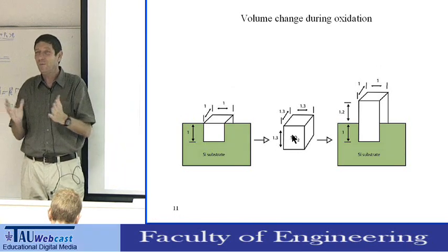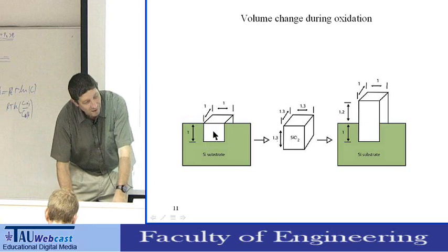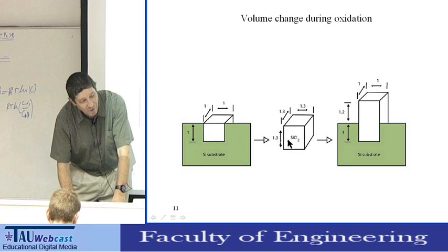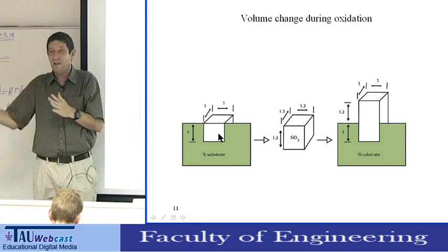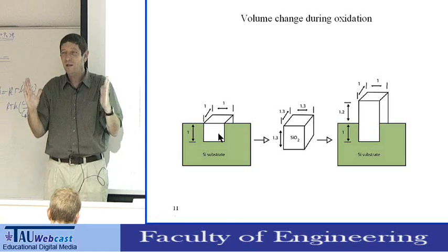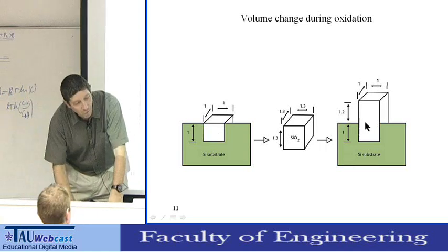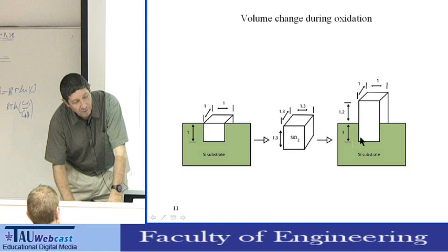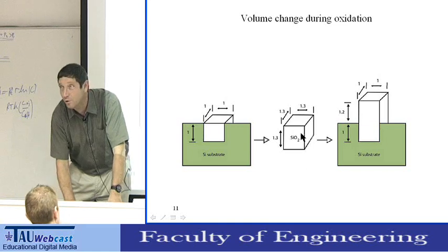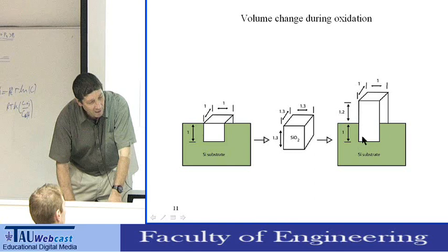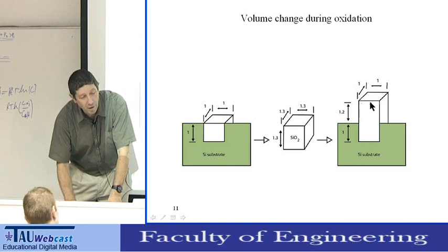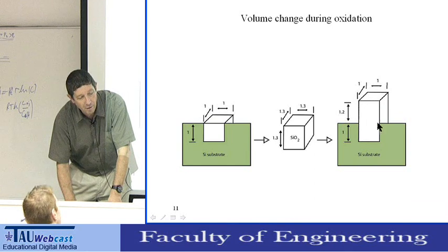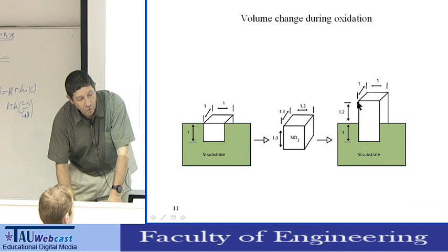But that's impossible, because the volume next to it will also generate the same structure, and the volume on this side will always generate the same structure. So this volume, because it has neighbors from right to left, will stay 1 by 1 on the bottom. But since the total volume should be 2.2, it has to grow about 1.2 upward.